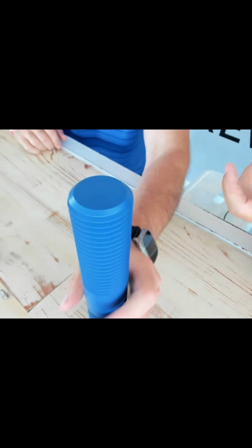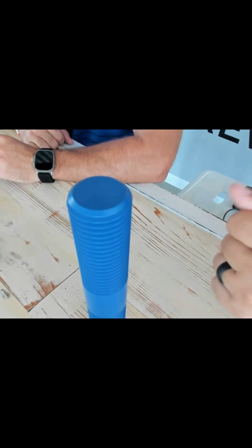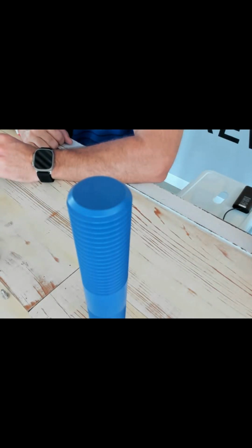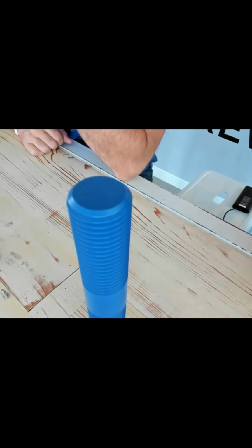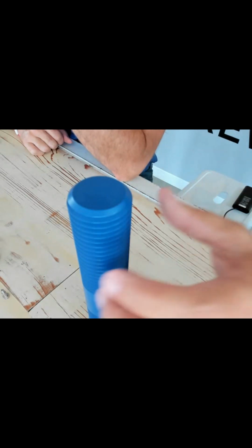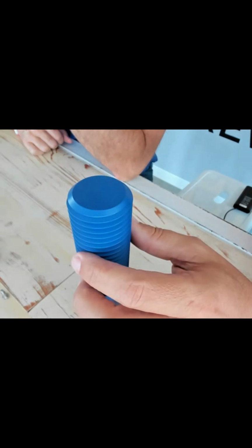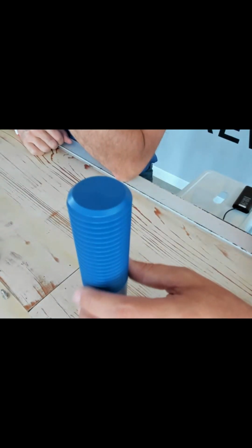So, another thing to mention on PTFE too, Bryce, is that top coat is generally applied by a person spraying this. So you're spraying around the outside with a gun that's very similar to an auto body gun, right, where you'll spray an auto body. So it is prone to somebody laying on a little heavier in one area, a little lighter than the other. Yep. So it takes some skill and it takes some control in the operation to ensure that the consistency of the thickness is the same, in the crest of the threads, in the root of the threads, on the tops of the surfaces, really just everywhere.